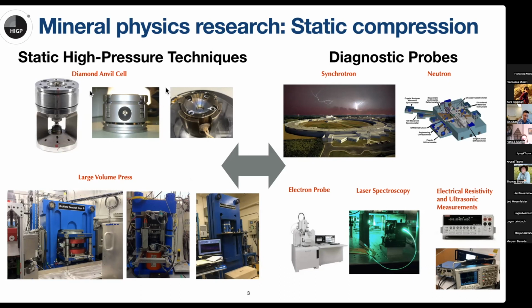Those static high pressure techniques can be combined with diagnostic probes. We often combine them with synchrotron X-rays, neutron sources, and laser spectroscopy. If the sample is recovered from the high pressure experiment, we can use an electron probe to analyze the composition of the sample. Sometimes we also combine electrical resistivity and ultrasonic setups for measurements in the multi-anvil press, and the electrical resistivity setup can also be used for diamond anvil cell experiments.